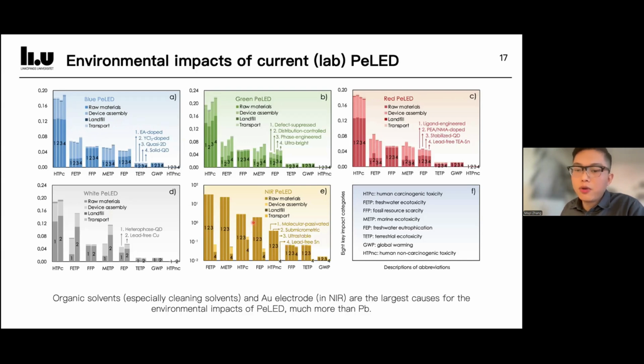Near-infrared LED show very large impact due to the use of gold electrodes. Gold has a very high energy consumption and pollution associated with gold mining. So this slide tells us organic solvents, especially cleaning solvents, and gold electrode in near-infrared are the largest cause for the environmental impacts, much more than lead.